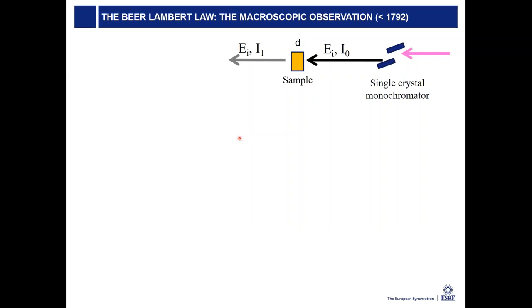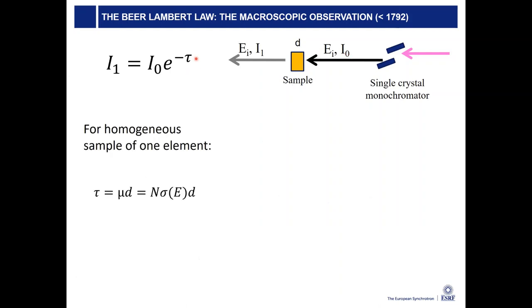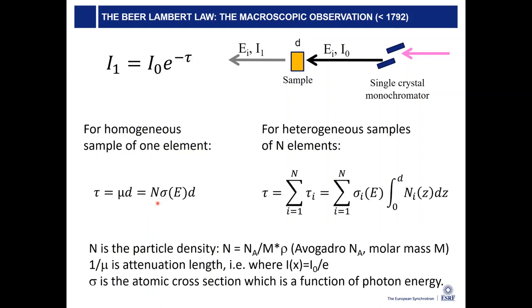Let's take a step back and go back in history. How was absorption described in 1792? The Beer-Lambert law, which is a kind of empirical law, shows that the intensity after a sample is reduced compared to the intensity before the sample by this exponential factor. And the tau here I can then describe in more detail by the particle density, and here this is the atomic cross-section of the atoms in the homogeneous sample. It's a little bit more complicated if you have a heterogeneous sample with several elements. It's just a sum over the cross sections of the different elements in the sample.